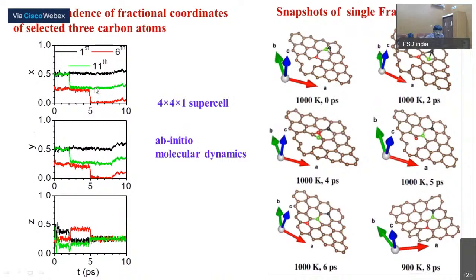The colors black, green, and red correspond to these atoms, and we show how each atom moves with time. This is the initial structure, and we see that at about 2 picosecond this black atom pushes the green atom to this position, and then after some time the green pushes the red, and then this comes here, and finally at about 6 picosecond we get a perfect graphitic layer. But at 900K when we do the simulation, we find that the lattice is not fully annealed, and we find that there are 5 coordinated and 7 coordinated structures in the lattice.